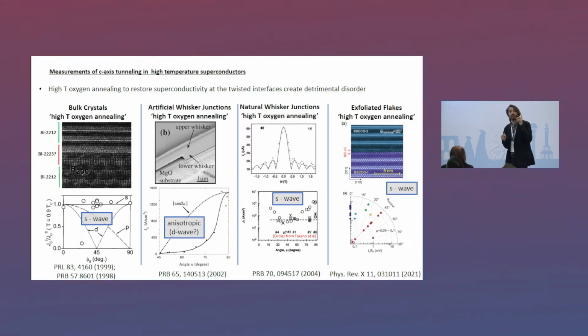But if you speak about the C-axis Josephson junction, which has all the interesting properties I'm speaking about, and which people have tried for a long time to realize, then you have a coherence length of 0.1 nanometer, which means that for realizing microscopic devices you need angstrom precision. People have realized vertical junctions using BSCCO, for example, bulk crystal in 1999, whisker junctions, and so on, and even recently thin flakes. All these methods showed approximately no angular dependence of the critical current density, except for the whisker, where however the cosine dependence that you expect from d-wave was not very evident.